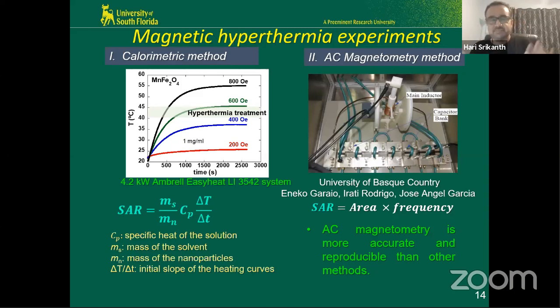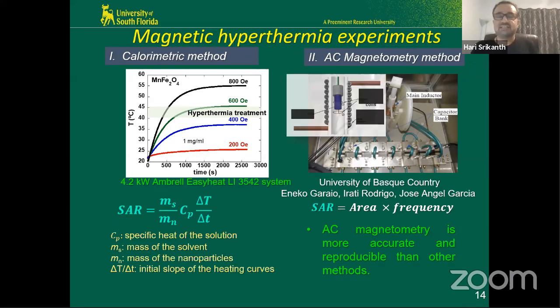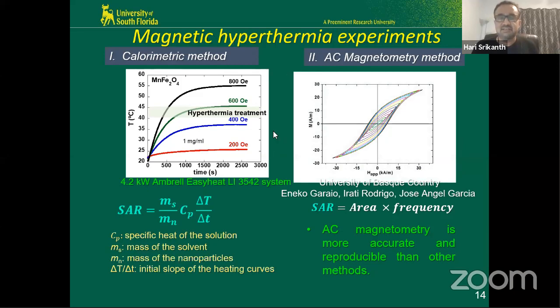Okay, so they have this big, large AC magnet that they've developed to apply large magnetic fields, a high power magnet, and essentially their data looks like this. And they can actually measure the complete hysteresis loop and get the area inside the loop. Okay, in that case, they get the SAR. So you see SAR on the same particles. We do it with two different experiments.